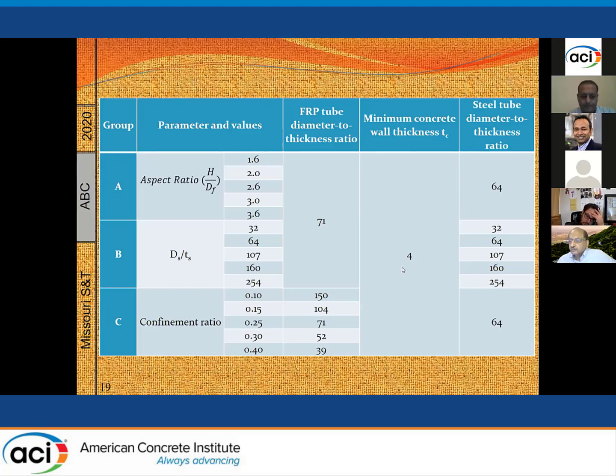or 10 centimeters. And then for the steel tube diameter to thickness ratio, for group A, we have diameter over thickness at 64. On group B, we played with the diameter of the steel and the thickness of the steel. So we changed the D over T for the steel pipe, moving from 32 to 254.